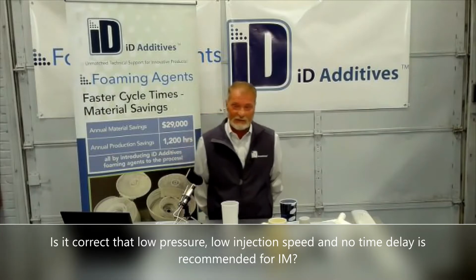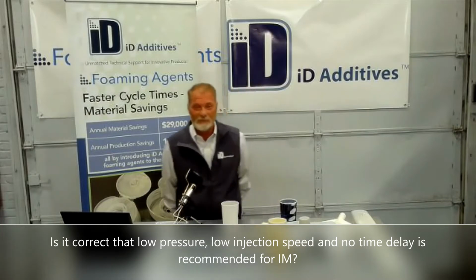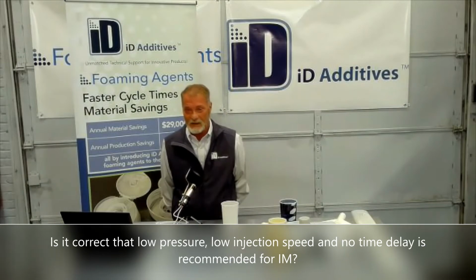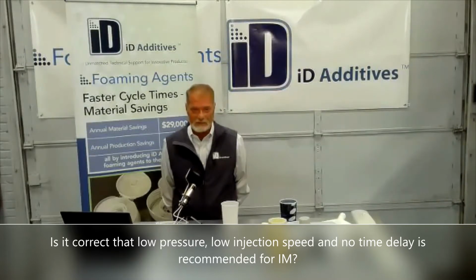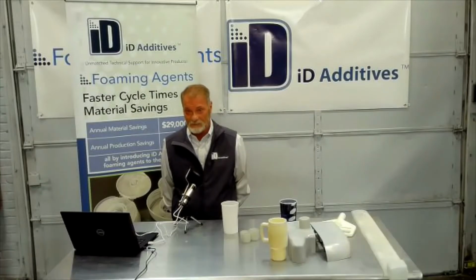The gate freeze is not pressure and time, it's just time. So you use the pack time. No delay time, agreed. Low injection speed, no. You want fast injection speed, as fast as the machine will do. Every trial I go to, whatever that machine will do, I'm going to do it.